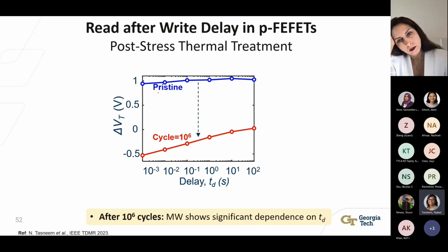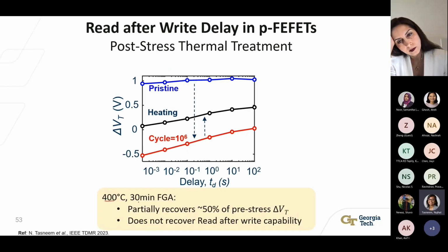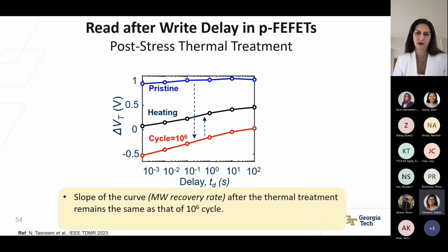So to reiterate, when we go from pristine to 10 to the power 6 cycling state, PFET loses its immediate read after write capability. Now, if we do a thermal treatment that includes a 400 degrees Celsius, 30-minute forming gas anneal, we see that, interestingly, the memory window of the p-type FEFET partially recovers by around 50%. However, the read after write capability of PFET does not recover. And also the slope of the curve, or the memory window recovery rate after the thermal treatment, shown by this black curve over here, remains almost the same as that for the 10 to the power 6 cycled one, which is shown by this red curve over here.